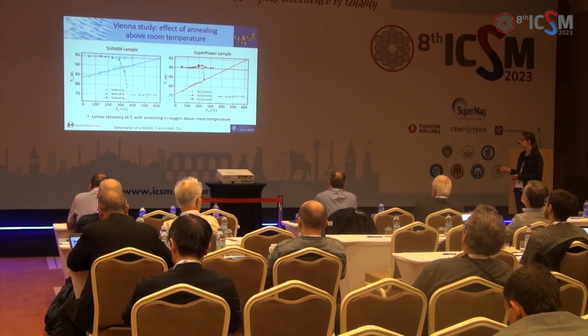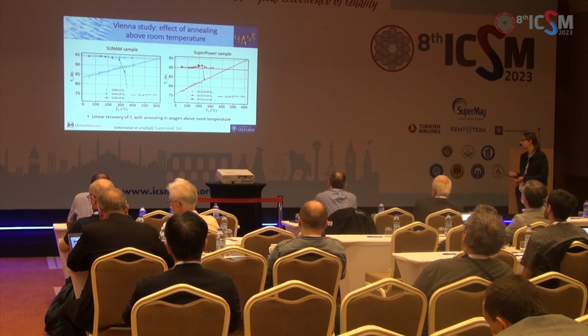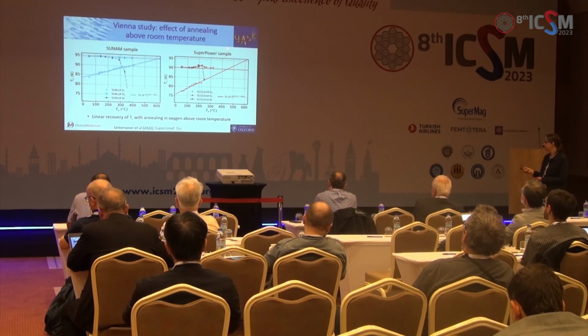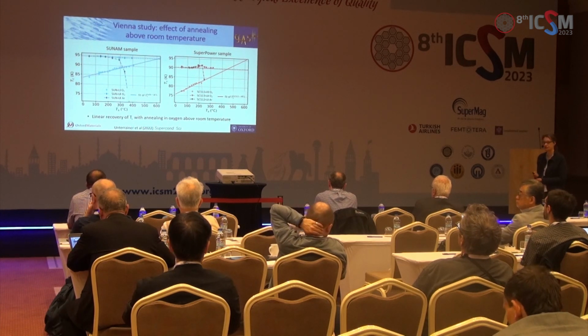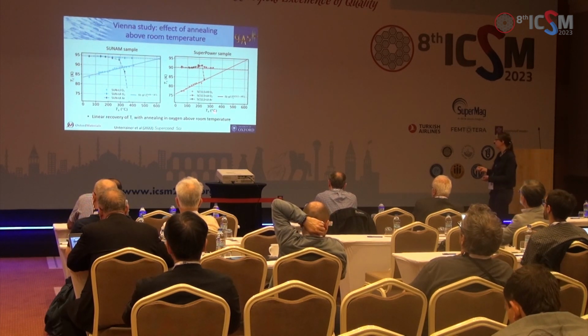Out of interest, this is the argon annealed sample, so you can see if you anneal in argon, you pull out oxygen and it gets worse. Same thing happened with the superpower samples, but something odd happened with this sample here, so I'm not entirely sure. They couldn't carry on getting this recovery here.